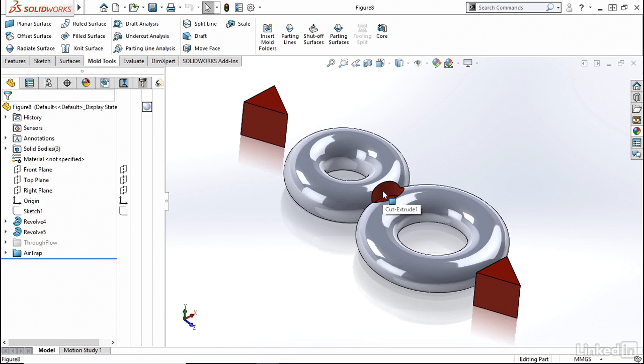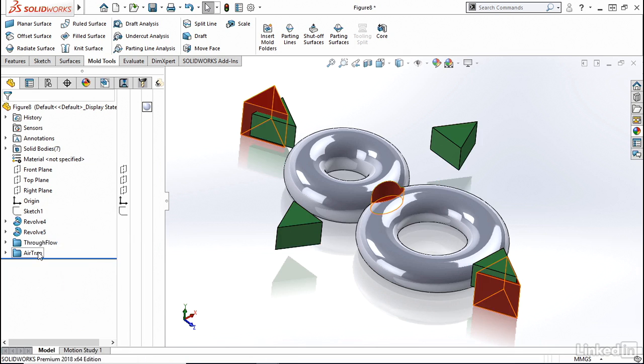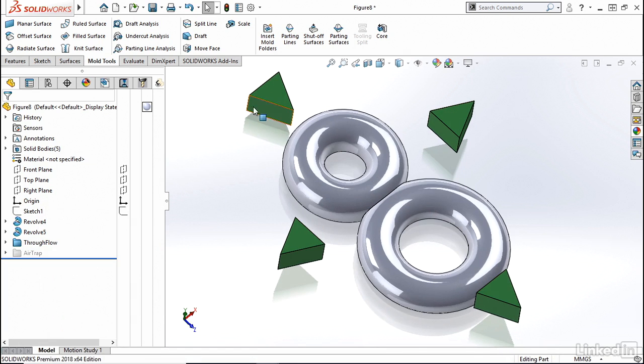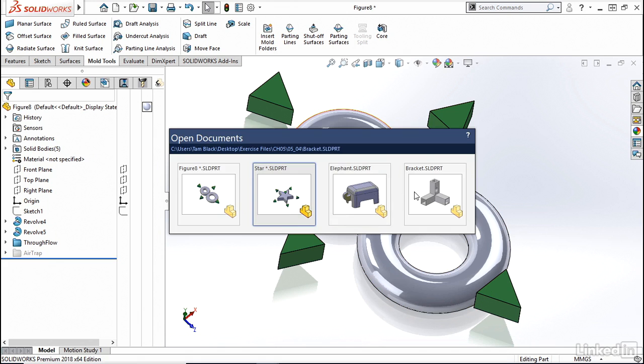Gas traps are usually due to inadequate venting. The air being displaced by the plastic has to go somewhere, ideally out of the mold. For example, two masses of material move toward each other, but there's nowhere for the pre-existing gas to escape to, so it gets trapped in the plastic. Watch out for voids along knit lines in tight areas or features that are too thin to fill in properly. This would be an example that has an inflow at one point of material introduction and has outflow in the middle of this figure 8.